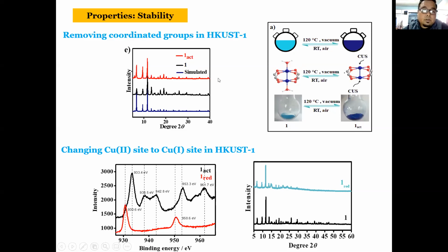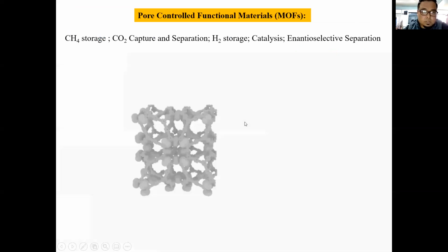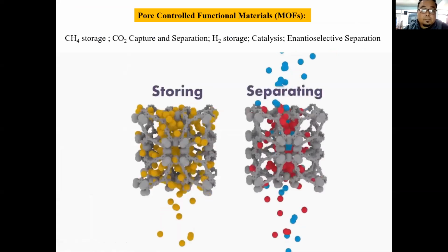But if we look at the powder XRD, we see that both the structures are almost stable. And yes, this process is highly reversible. So it again comes back, and this structure will become again the unactivated form. So again, even with this copper 2 ion, if we reduce it completely to copper 1 ion, we still see that the structures are almost stable. I haven't shown the structural stability part.